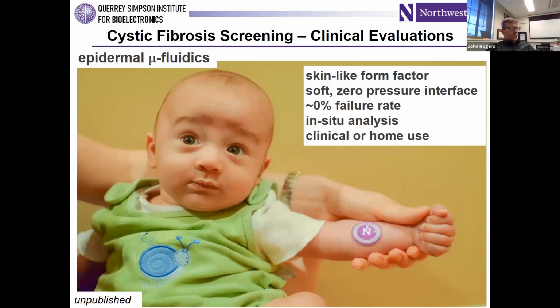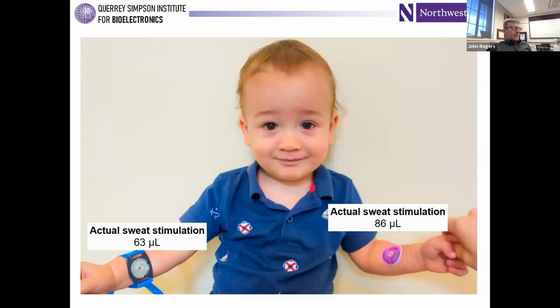It's very simple. It's just a soft adhesive interface to the skin. You capture the sweat. You've got the chloride analysis capability built into the patch, so you don't have to worry about loss of sweat during transfer to a separate analytical instrument. And this looks like maybe an initial application as a medical diagnostic. And so we've probably done 50 patients so far, and it's looking quite good. We're typically collecting significantly more sweat, and again, we do in situ analysis, which greatly facilitates the process and actually allows it to be done in the home, which is going to be really interesting and super convenient for patients.